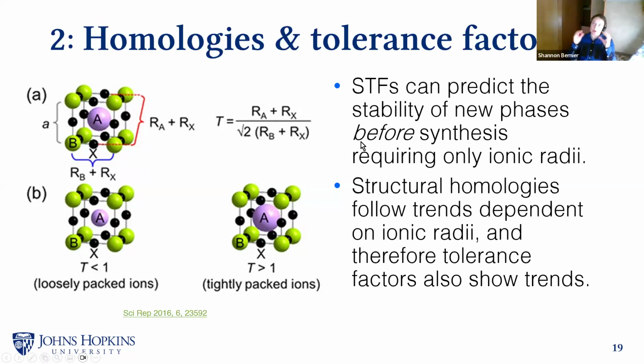So we wanted to emphasize to others in our field specifically that the cubic deviation metric is not a tolerance factor. It's not designed or even able to be applied before you've made the material, because you have to have a measure of the lattice parameters, which you won't know until you've actually made the material and performed diffraction, or if you're doing a computational study, until you've already refined and optimized the position of atoms in a theoretical unit cell.